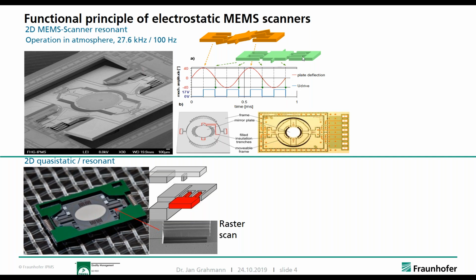So the electrode combs are in plane, as you see here, and then you apply a rectangular voltage as seen here, and the mirror plate is driven towards the rest position. You always have a little bit of asymmetric fabrication. A few nanometers are enough there in order to get an oscillation started. And you turn off the electrostatic voltage in rest position so that the mirror can be driven through by its inertia forces. Then you have to get the right point again at the maximum amplitude of the mirror, and you turn on the voltage again. That way you have the most efficient drive for these electrostatic scanners.